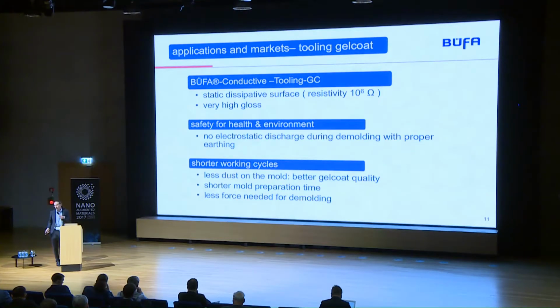And we found this is a big bonus for our customer because he has more safety for the workers and also for the environment. Over the last years, 1 up to 3 customers have had some burning accidents in their production, and sometimes you have burnable liquids from the release agent or something else near the GRP mold, and at the moment when you demold, you sometimes have really big lightning strikes, and if it goes to the burnable material, you have a problem. And it's also painful for the first person who contacts the mold. It's very painful. These sometimes are up to 30,000 volts at the moment of demolding.